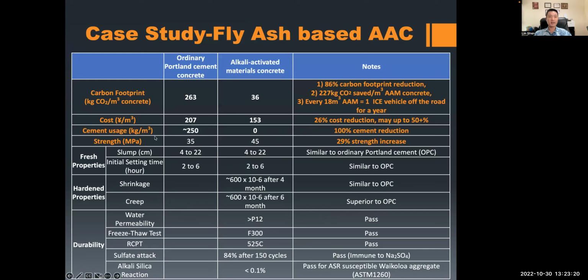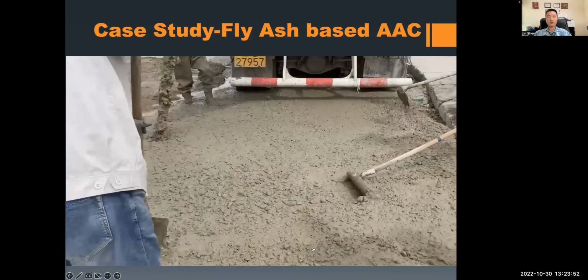It does not use any cement, so 100% cement reduction. Strength-wise, very good, about 30% strength increase. Fresh properties, such as slump and setting time, are pretty much comparable to normal concrete. Shrinkage and creep are similar. Durability tests are all pretty similar, sometimes even better than normal concrete. And here shows the video of pouring the AAC. This is in one of the provinces in China.